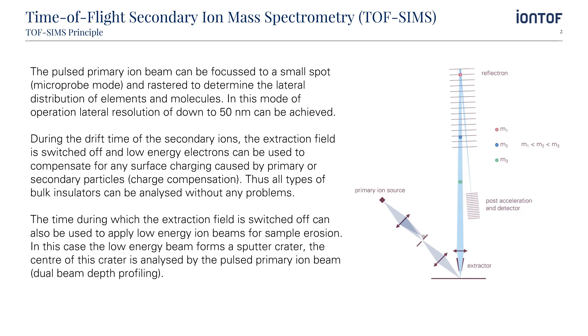The time during which the extraction field is switched off can also be used to apply low-energy ion beams for sample erosion. In this case, the low-energy ion beam forms a sputter crater. The center of this crater is analyzed by the pulsed primary ion beam — dual beam depth profiling.